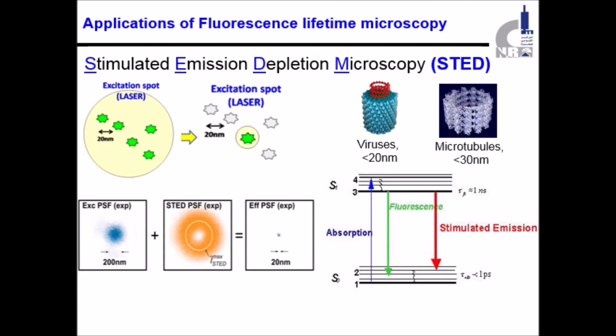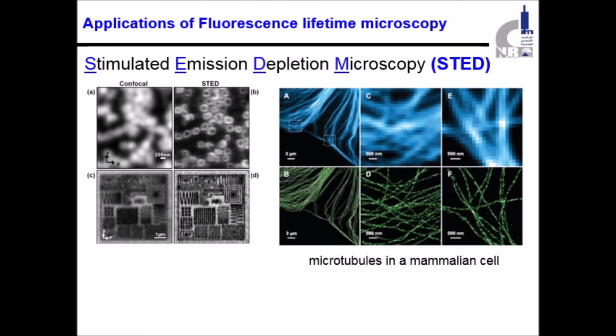The shape of the image using two types of laser source in this method seems to be a donut, and at this time we can image the molecule below the 20 nanometer scale. By using this technique, we enhance the contrast and the resolution of the image, as we see in this studied sample. At this time, we don't need a computational reconstruction as we did before.